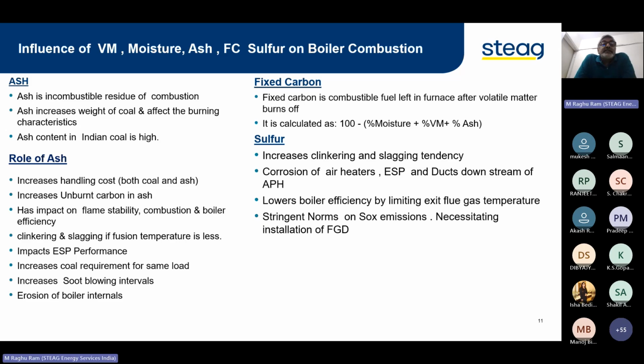Sulfur, what is the influence of sulfur? It is not a component generally expressed in the proximate analysis. However, it has a bearing on the clinkering and slagging tendency of the coal. That's why I touched upon it here. There is corrosion of air preheaters, because high sulfur content means formation of SOx products, and the air preheater exit flue gas temperature is limited. We cannot go below 125 to 130 degrees, which means a higher loss in the dry flue gas. If you go below, it will corrode downstream equipment like the ESP, ducts, ESP walls, and even ID fan ducts. So it also lowers the boiler efficiency by limiting exit flue gas temperature, so it has a bearing on dry flue gas loss.